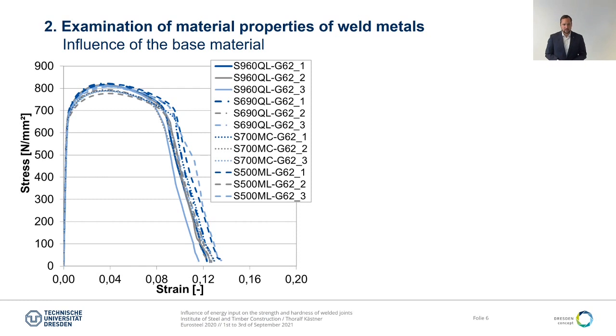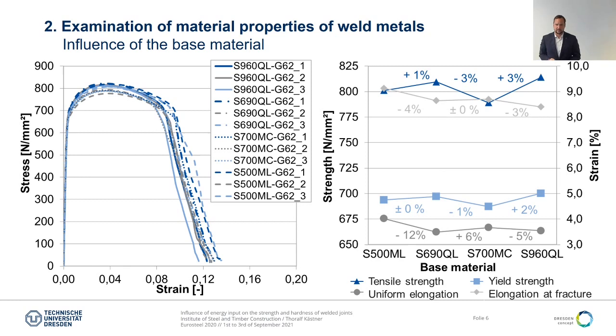So first of all, I want to give you an insight into our experiment on the influence of the base material. What you can see here on the left side are the stress-strain curves for all the 4 base metals we examined in combination with filler metal G62 for a cooling time of 12 seconds. And what we can see is that there are no significant differences. Having a closer look at the mechanical properties, we can see that the base material has more or less no influence on the strength properties.